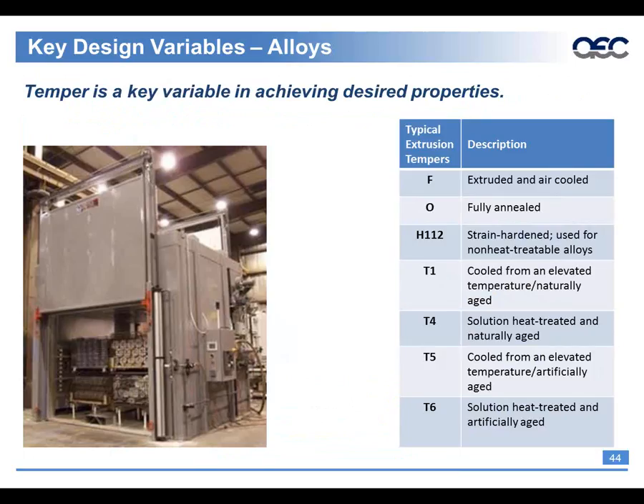F temper is kind of, you get what you get: you extrude it, you cool it a little bit. There are really no properties that go with it. Annealing it, you're heating it up at a very high temperature for a certain period of time. You're almost essentially overaging it, but you're getting it to the point where it's very easy to form. It's very ductile, so if you have things that you need to bend or shape, it's a good thing to do. H112 is really not applicable for this discussion. It's not applicable for 6000 series.